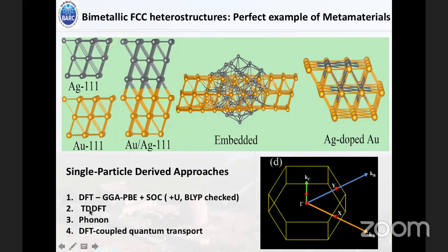And we have treated all these systems by using some single particle derived approaches, which are DFT and GGA-PBE plus spin-orbit coupling. And also, I must mention here that we have taken care of all scalar relativistic corrections. And also for a small model system, we have checked with GGA plus U and hybrid functional calculations, so that we can tell that this GGA-PBE calculation, whatever we have done for this system, is a stable calculation. So next, we have done some time-dependent DFT calculations. Phonon calculations were done, and then DFT coupled quantum transport. All are single particle derived approaches.